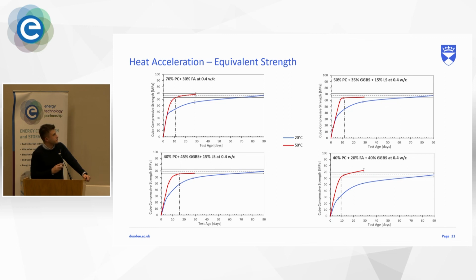Whereas with GGBS, that doesn't happen really. But this was known before that research, so this just plays well with whatever we found. That would explain why the concrete strength keeps growing with fly ash, because fly ash tends to kick in in the later phases.